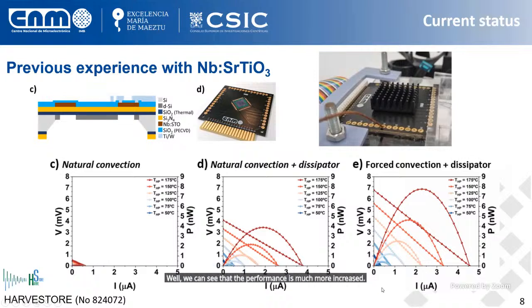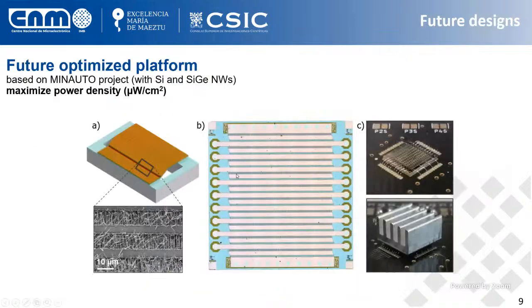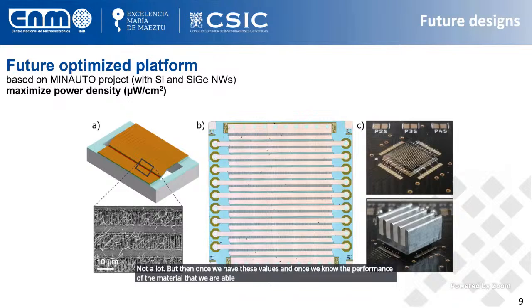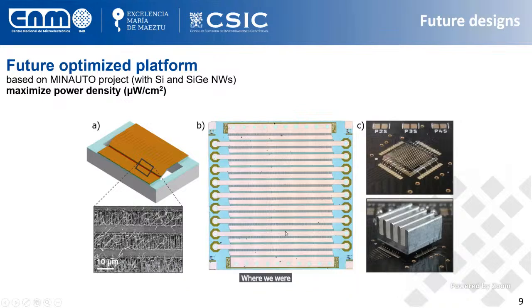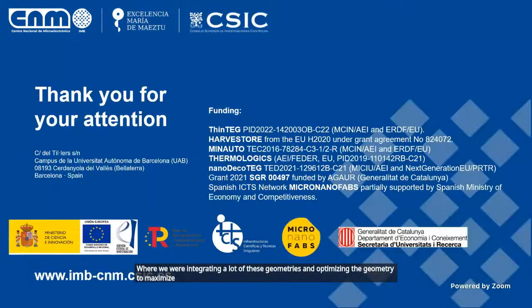Again, this is not the optimum geometry or architecture. This is just to test the device. You can see that the power output is quite low. It's around 8 nanowatts. But once we know the performance of the material that we are able to grow on these platforms, we will need to optimize them and try to increase the power density, with a structure similar to what we did in the silicon nanowire case, where we were integrating a lot of these geometries and optimizing the geometry to maximize the power output of this material.